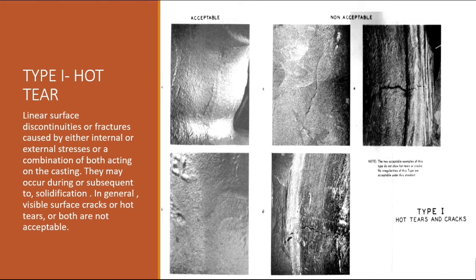So first we understand what is hot tear. Hot tear is basically a linear surface discontinuity or fracture caused by either internal or external stresses or a combination of both acting on the casting. They may occur during or subsequent to solidification. In general, visual surface cracks or hot tears or both are not acceptable. In many cases, hot tear can also happen when thickness variation is there, and in thickness variation when solidification occurs, less thickness will solidify early and higher thickness will solidify late. So due to stress generation, this kind of discontinuity may happen.